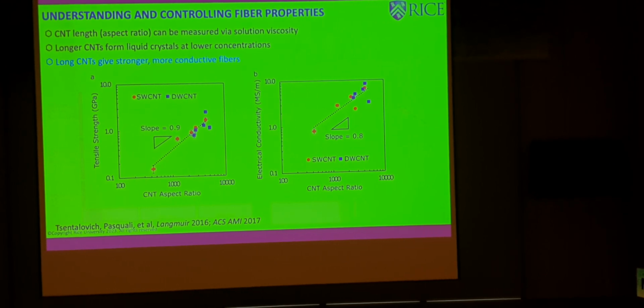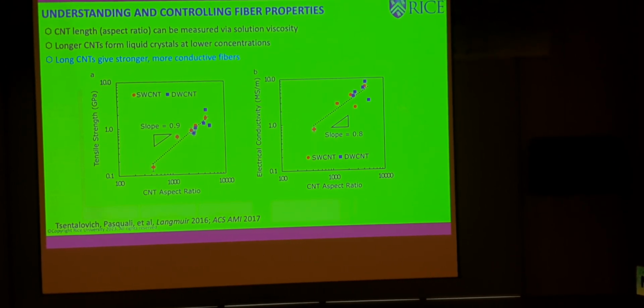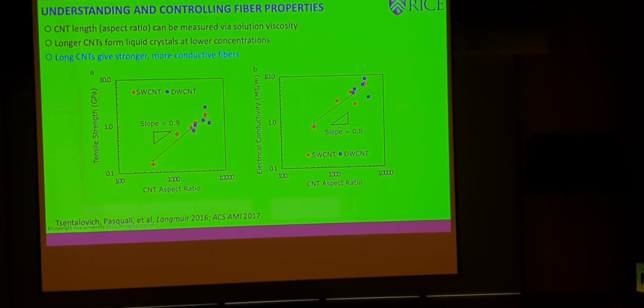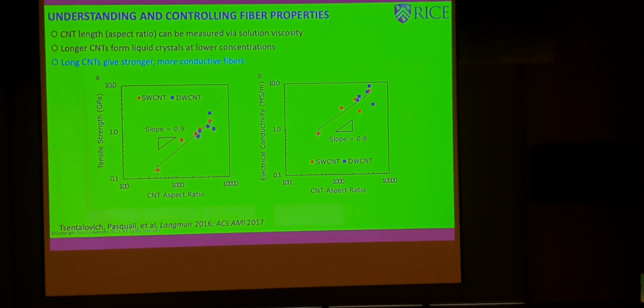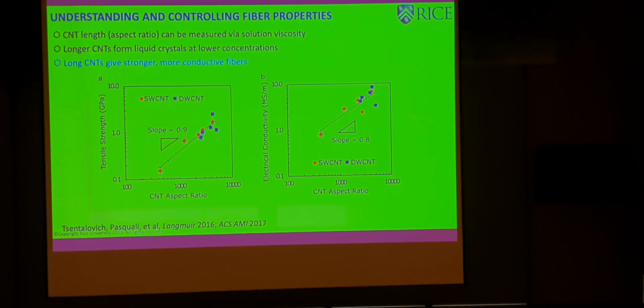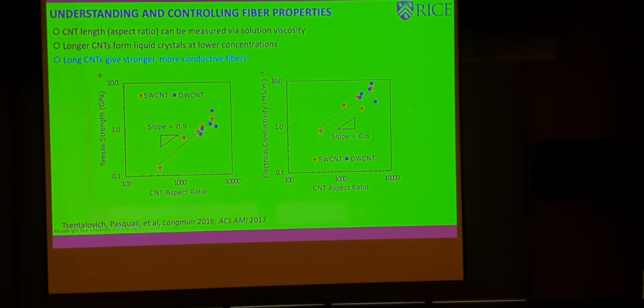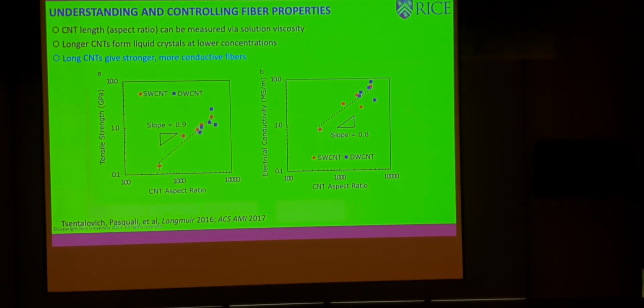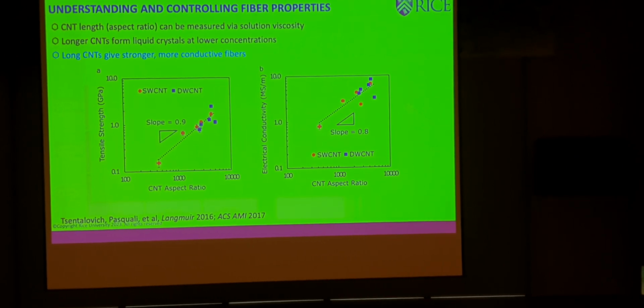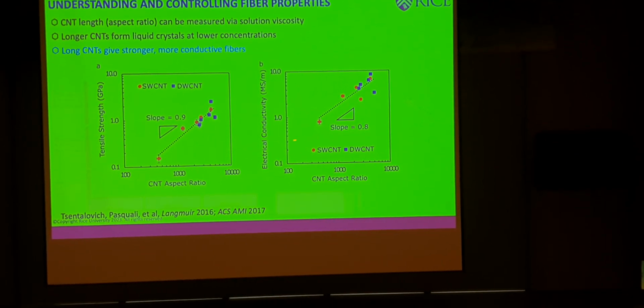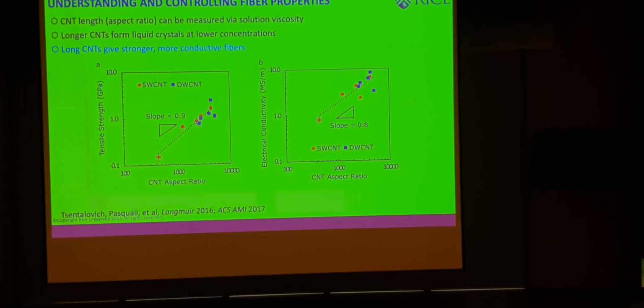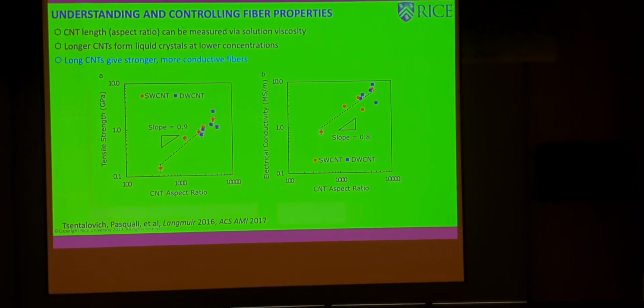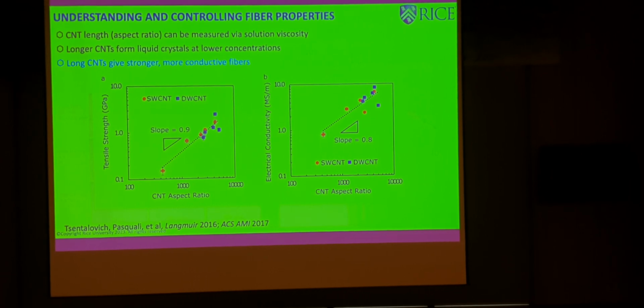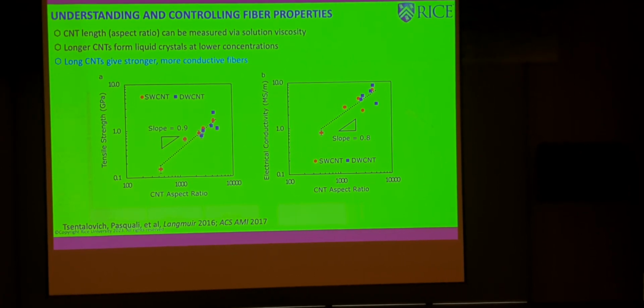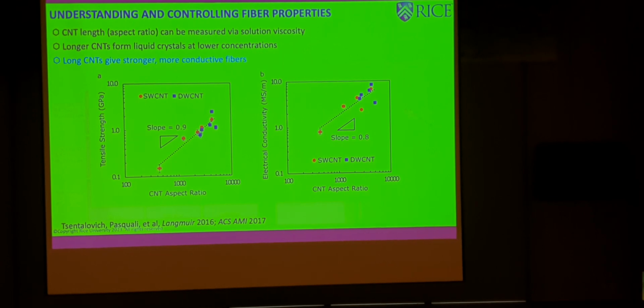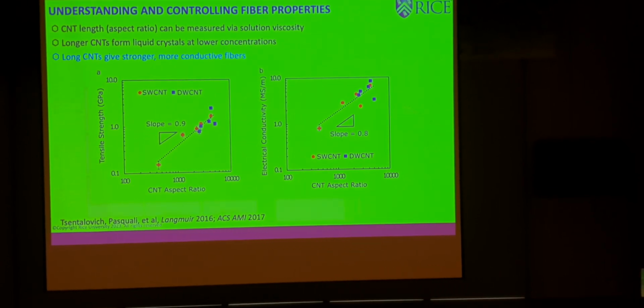So now that we knew how to measure length, we could make fibers with these materials, and we saw that in addition to crystallinity, which you measure by looking at the Raman G to D ratio, there was another property that was important, which is the aspect ratio of the nanotubes. And roughly, the tensile strength and the electrical conductivity scale, let's say, roughly linearly with the length of the nanotubes. This is not surprising. This is what you would have expected based on polymer processing, polymer properties laws.